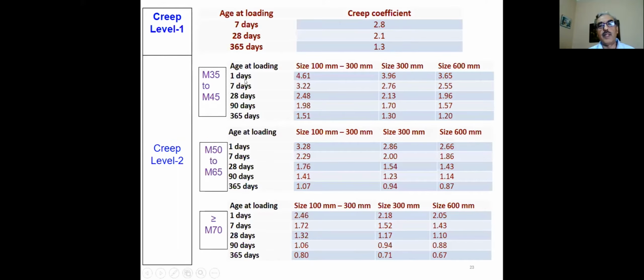In creep level 2, the values change with the grades of concrete. Three slabs are there: M35 to 45, M50 to 65, and for different sizes of members (notional sizes) you can relate your member to these sizes, along with the age of loading. These tables have been given. If you see the 28 days loading stage, there is not much change - for example here it is 2.1, 2.48, and when the sizes are bigger it is somewhat similar. So the only thing is it is a little more rationalized.